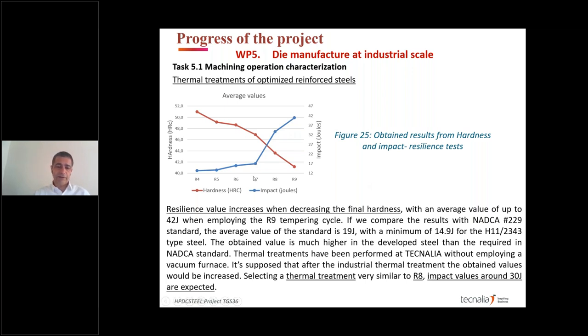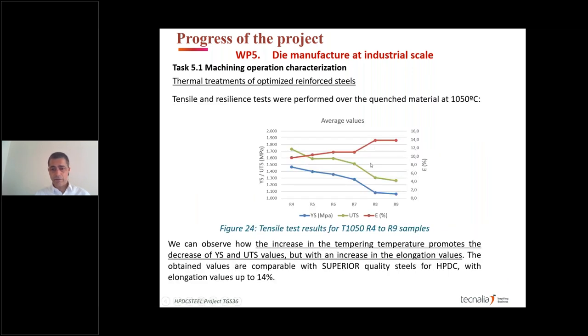So depending on the way that we define the final tempering process, we can have a very good, high impact property in the steel. Having all this in mind, we finally select this one up there, R8, which will give us more or less 35 joules of resilience. And if we go back, an elongation of about 8%, and ultimate tensile strength of about 1300 megapascals and yield strength of about 1100 megapascals.